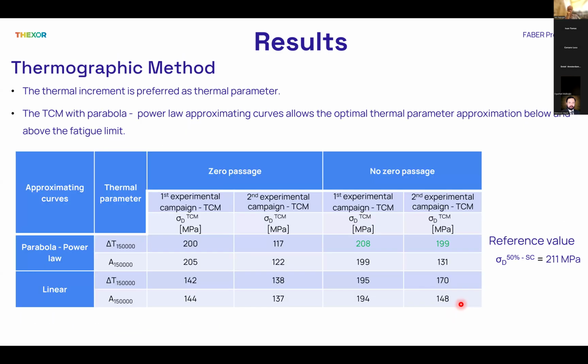This slide reports the results in terms of fatigue limit estimation using the thermographic methodology, but without any improvement from artificial neural networks. The analysis was carried out using these two thermal parameters, the thermal increment and the thermal area, but also using different approximating curves, the parabola power law approximating curves and the linear possibilities, and also investigating the possibility to set a constraint for the mathematical formulation below the fatigue limit.